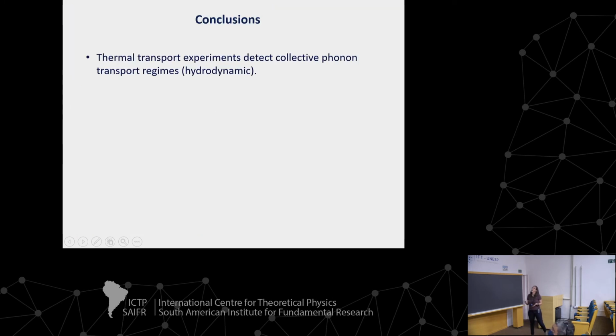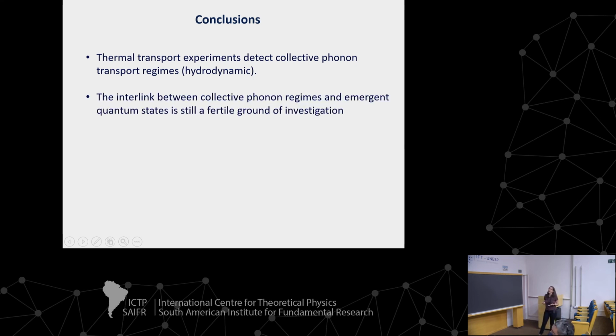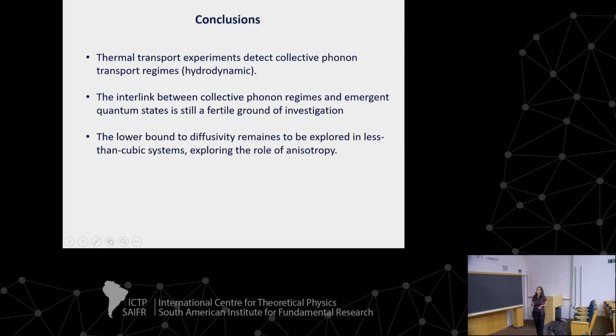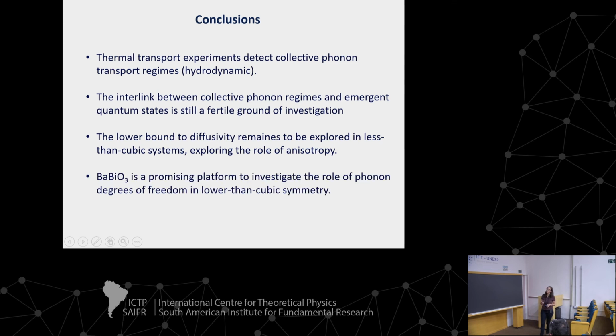So in conclusion, I want to point out that thermal transport can really detect collective phonon regimes. And so the interlink and the understanding of phonon dynamics can be quite insightful in terms of other emerging collective states. From the side of the high temperature investigation of diffusivity, it is still quite an open point to understand not only how we can understand better, but how we could manipulate the structure of the material to induce special regimes of transport. And finally, that BaBiO3 is a very promising platform.